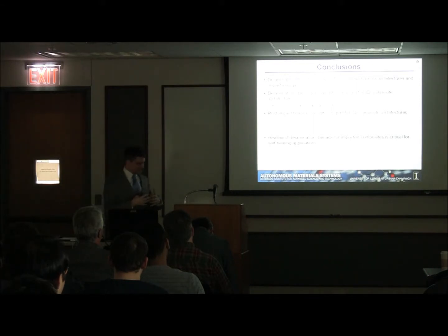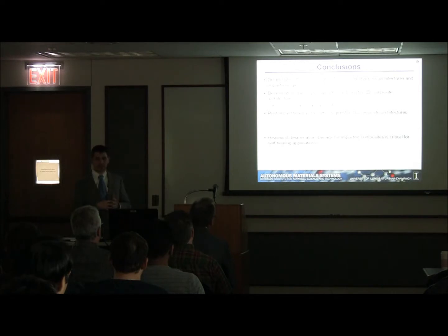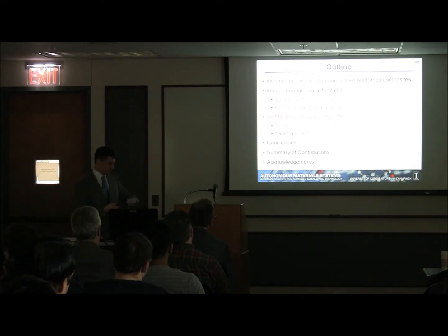So the big takeaway message as I thought about moving forward in self-healing is that it's healing of delamination damage that's important. It's this delamination damage that dominates the reductions in post-impact strength after the damage has occurred. So if we're going to use self-healing applications of vascular networks, we really need to target the delamination damage here. That brings me to the self-healing portion of the talk using vascular networks.